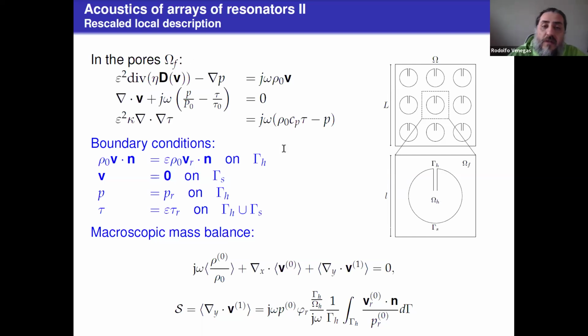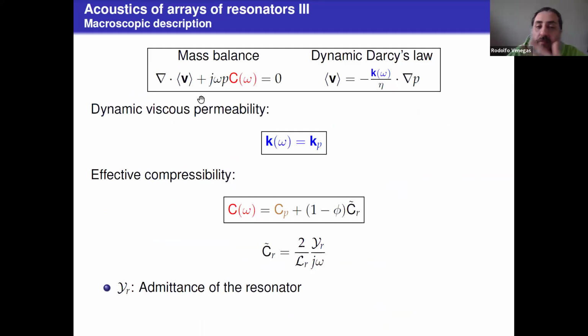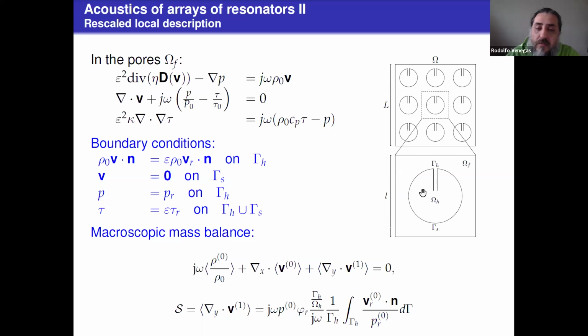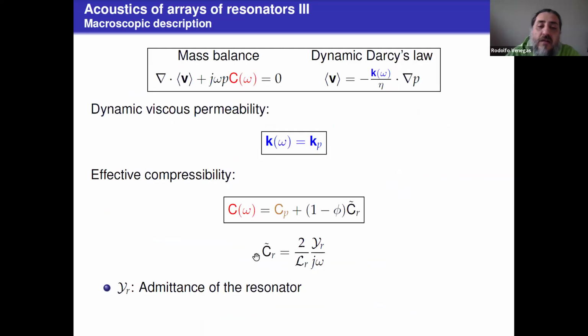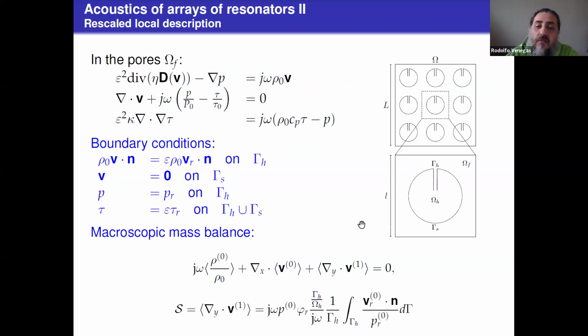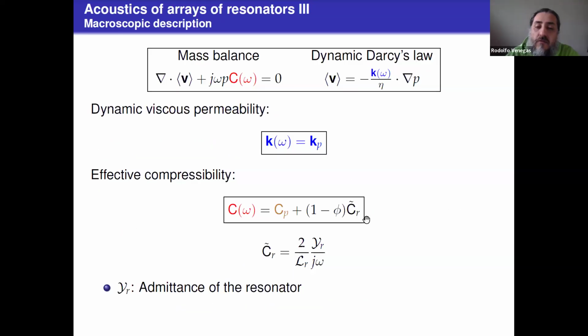Applying homogenization, we get the macroscopic description. Again, it follows the same type of structure, where the dynamic viscous permeability is determined by what's happening around this resonator. And the effective compressibility has two components, one of them coming from the pore, so around this resonator, and another one coming from the resonator itself, where CR is an apparent compressibility which depends on the effective admittance of this resonator.